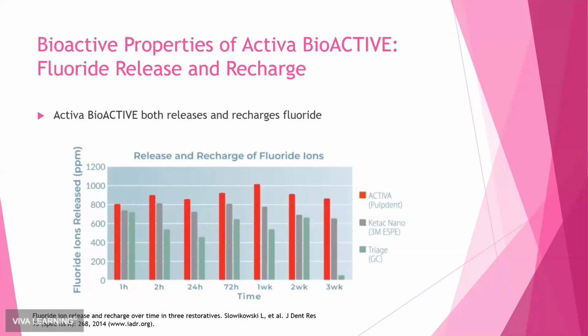So the fluoride release and recharge is probably one of my favorite properties of this material. This study shows Activa against Ketac Nano and Triage materials, and it looks at the fluoride release and recharge at various hour increments and also at 1, 2, and 3 weeks. We know that all of these materials release and recharge fluoride, but Activa definitely excels as far as the amount that's released and recharged. So in every instance from the starting point on, you can see that it's exhibiting the highest fluoride potential. It's recharging and releasing the most.